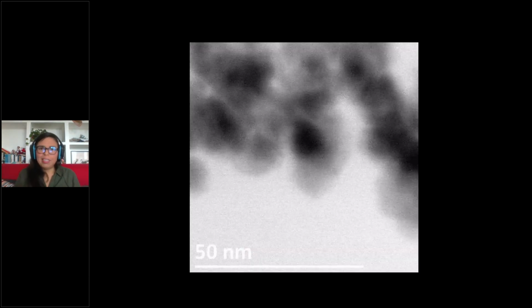So what we were able to track in situ, and was a very exciting day, was the day when we did this video. So we have our particles, we see a layer that goes away, retracts again towards the particle, and grows back again upon cycling. So what we think we are looking at is the amorphization of the surface of the cobalt oxide, which has been, as I mentioned before, already observed or determined by EXAFS measurements, but has never been seen directly like we are seeing here.